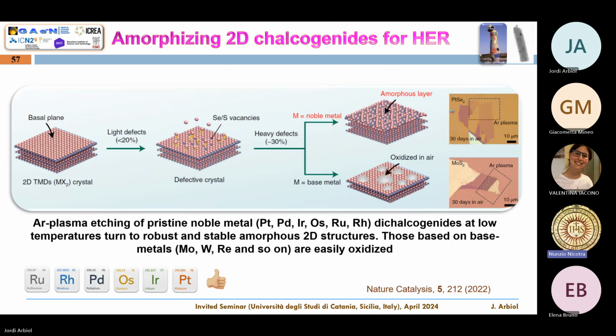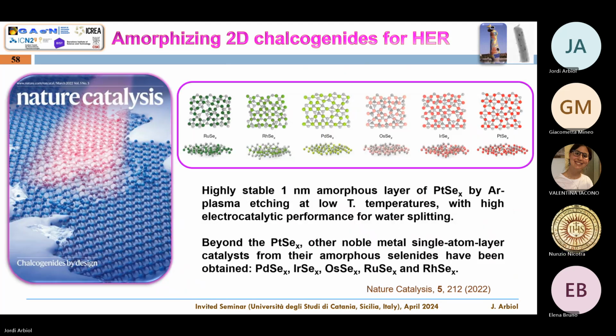wanted to show you. And then, yes, this works for all these noble metals. So you can create platinum diselenide, palladium, iridium, osmium diselenide, etc. It works for all of them. But if instead of noble metals, you use molybdenum, tungsten, rhenium, and so on, in this case, they are not so stable because they get oxidized quite easily after 30 days. You see that the material is decomposed. But in the case of the noble metals, they are still working after 30 days, okay? In nice conditions. They are still working.